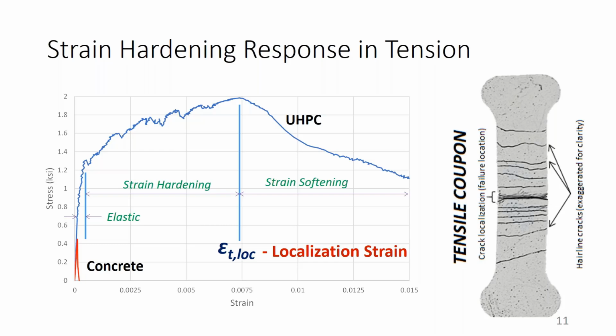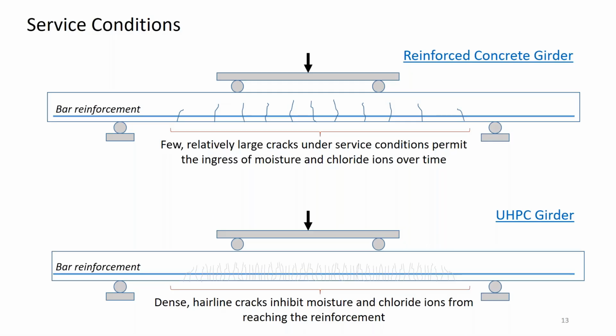You can see that the localization strain is about 2 orders of magnitude more than that of concrete. That is in the range of 50 to 100 times. The toughness is many orders of magnitude more as well. And this is a picture from a test where you can see the localization strain. You can see the fibers that were trying to sew it together, but they couldn't and failed. You can see, if you look carefully, the very fine hairline cracks fanning around this particular crack here. Okay, those are the types of cracks that I mentioned.